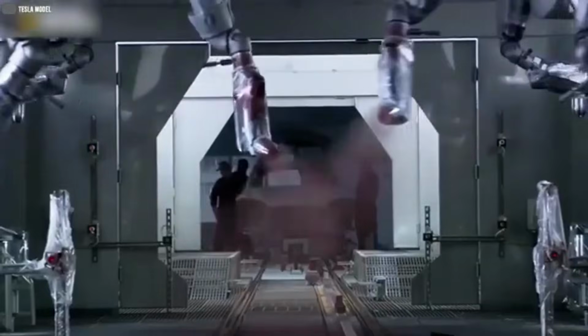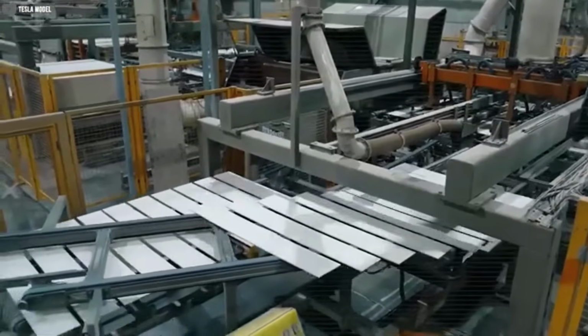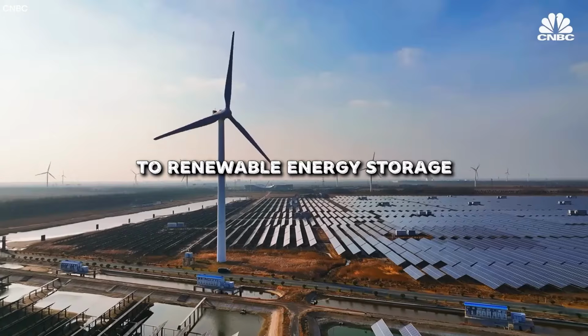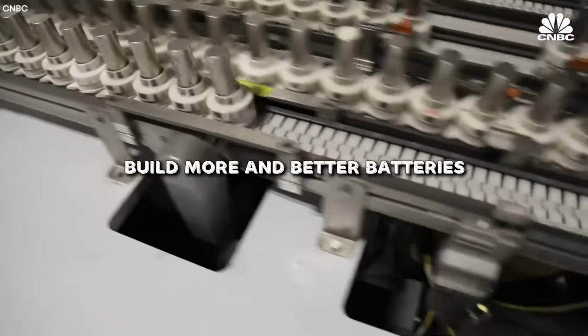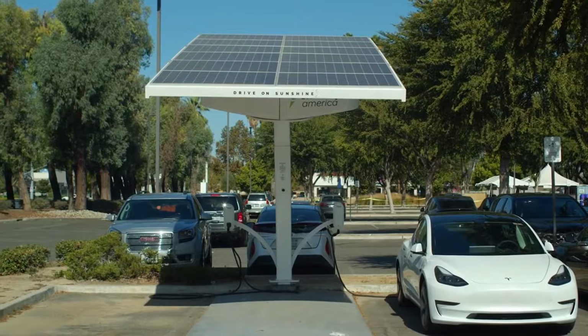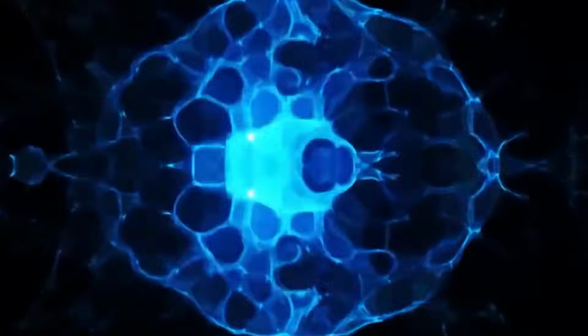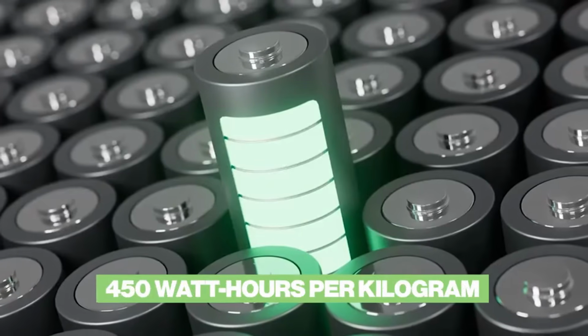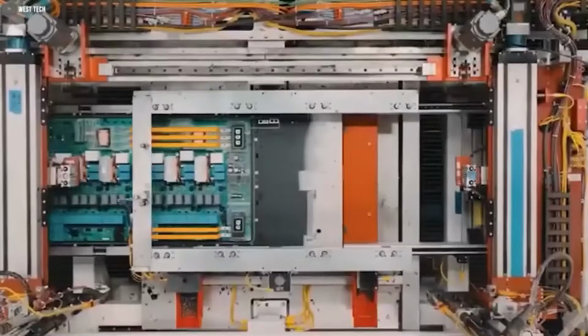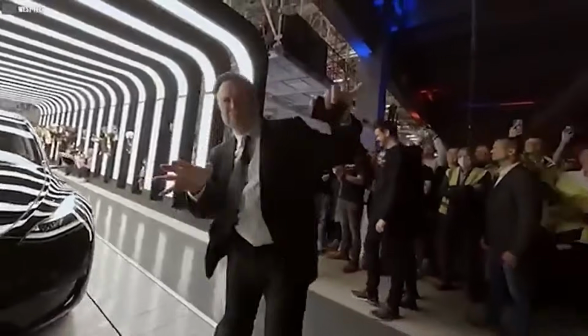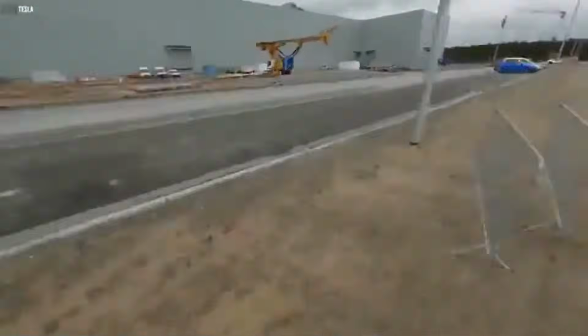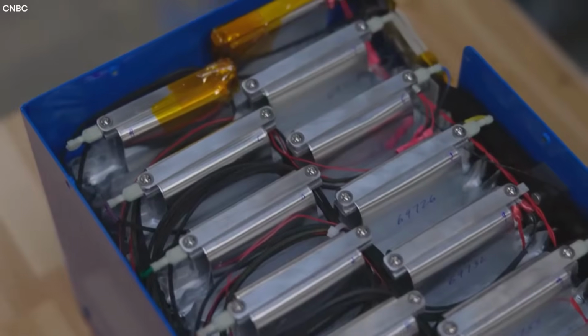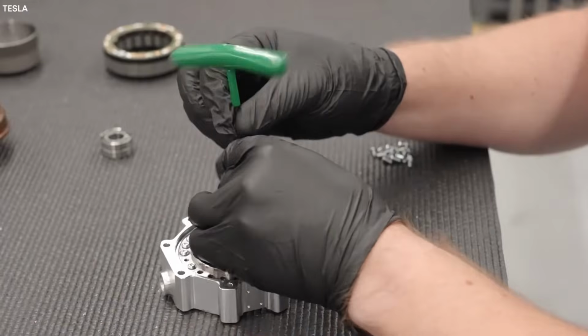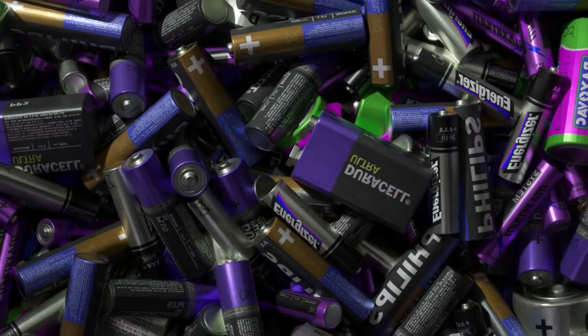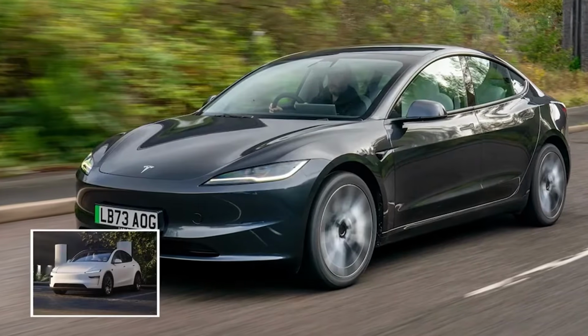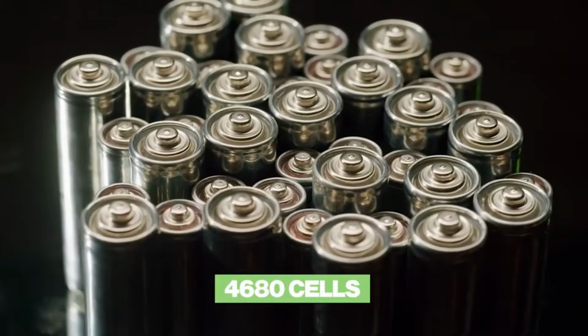On the cathode side, Tesla has opted for a high-nickel, low-cobalt composition, a shift that began with the 2170 and 4680 cells but is now refined to new levels. Traditional NCA, nickel-cobalt-aluminum, cathodes typically contain 80% nickel, but the condensed battery's formulation pushes this to 88 to 90%, drastically reducing cobalt content, which is expensive, ethically controversial, and environmentally damaging to extract. This change not only improves energy density but also aligns with Tesla's broader supply chain goals, reducing reliance on cobalt mining in the Democratic Republic of the Congo and increasing use of North American and Australian nickel sources.